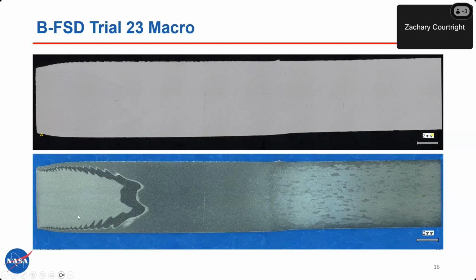And really only so you can kind of see where the grain refinement goes back to a rolled condition on the right. So that's like the nugget starts there and goes to the end. So that's like 1 inch, that whole area. So that area where the filler material is being mixed in goes well beyond the 1/8 inch deposition. So where Joseph's pointer is, that's about as far as the actual deposition height goes. But then as you can see, it's stirring back into at least the last few layers. So that really helps to show where that filler material is going.